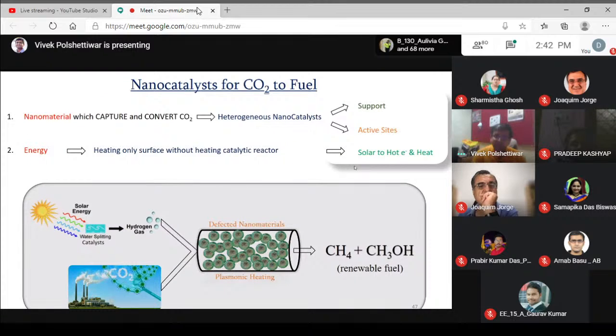How do I design these nanocatalysts which have the ability to capture CO2, harvest solar energy and react the hydrogen gas coming from the water with CO2 to produce methane and methanol? So this is what we do in our lab. The way we do it, we have a 3-component system. You need a support of some very high surface area material. Then you need active sites, which have the ability to capture and activate the CO2, capture the hydrogen or water and split water into hydrogen. And then you also need energy, and we want the energy to come from the sun.